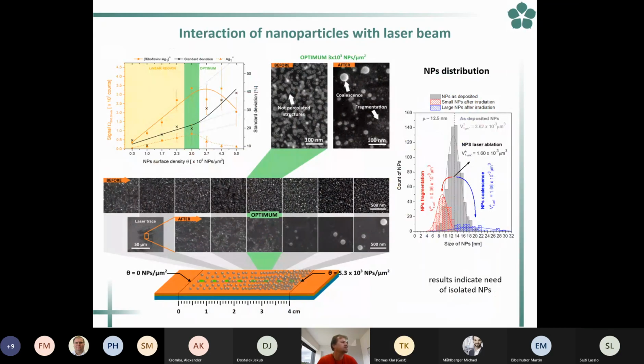Further on, we are also dealing with these nanoparticles as species for the detection. For example, as it is LSPR or SERS. Here you can see a screen from our former study where we studied how the nanoparticles behave with the interaction of the laser beam. That was quite important for us when these surfaces were used for the MALDI. This is the matrix-assisted laser desorption ionization spectroscopy. This is more or less mass spectroscopy, which is